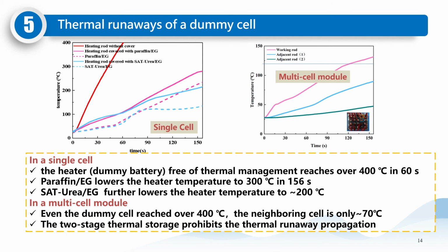And in the thermal runaway cases, we can see that compared with the paraffin, the salt hydrate could reduce the battery temperature from 400 degrees C to less than 250 degrees C. The temperature is lower than in the paraffin cases because it has thermochemical storage plateaus. Here we can see that, and in the multiple cell module, with the salt hydrate, it can also